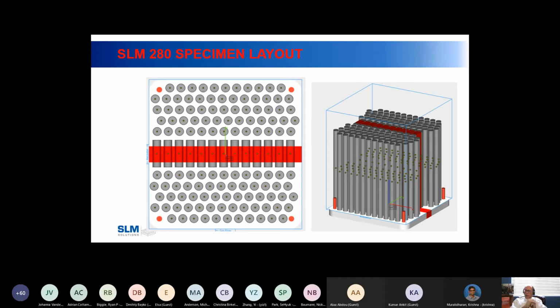So how do we do that? So here's a SLM 280 layout. And it's basically going to be 280 millimeters cubed in each direction. So here you have 100 vertical specimens, and of those vertical specimens, an E8, you can get 3 E8 specimens out of each vertical column. So if you got 100, you basically have 300 test specimens.